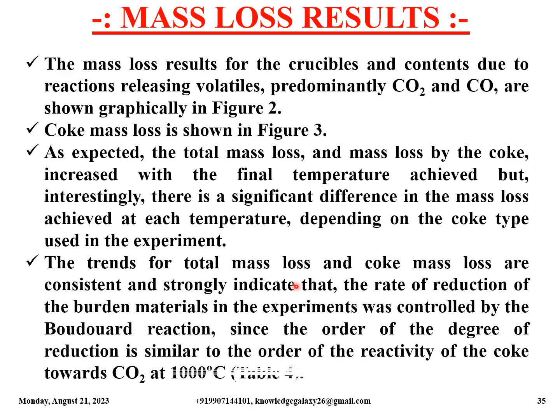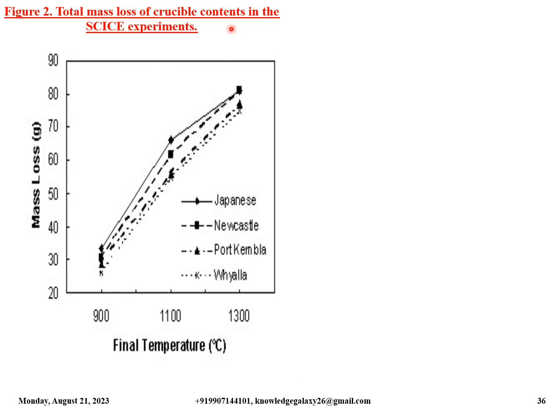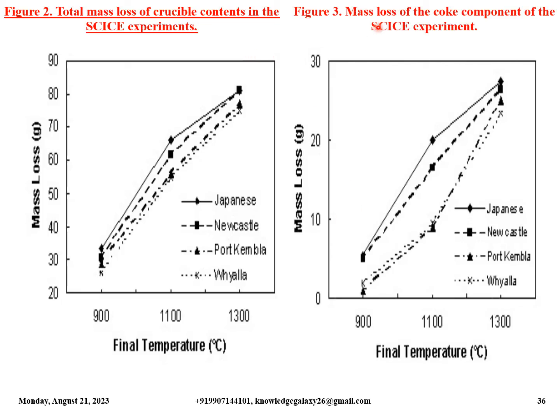The trends for total mass loss and coke mass loss are consistent and strongly indicate that the rate of reduction of the burden materials in the experiments was controlled by the Boudouard reaction, since the order of the degree of reduction is similar to the order of the reactivity of the coke towards CO2 at 1000 degrees Celsius as shown in table 4. So this is the figure of total mass loss of crucible contents in the SCICE experiments, and this figure represents the mass loss of the coke component of the SCICE experiment.